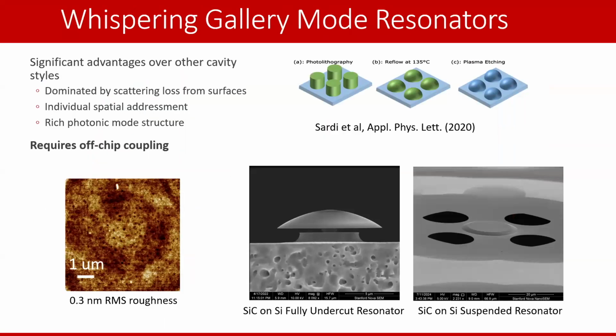Okay, so if you're doing cavity QED, you need a cavity. Much of the work in cavity QED in solid state platforms is often done with photonic crystals. That's because they tend to have excellent Q over V, which, if you remember, is one of the parameters we're very interested in for the cavity QED system: the coupling strength between the defect and the cavity mode. This scales as the quality factor over the mode volume. As a result, photonic crystal cavities tend to have very low mode volumes, and so even with modest quality factors, you can reach this strong coupling regime. Very, very high Gs.